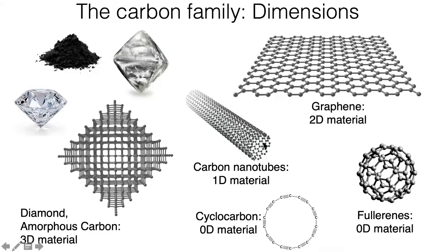Now let's go on to carbon nanotubes. If you imagine you take that graphene sheet and roll it up into something that looks like a toilet roll tube, you can see the hexagon all wrapped around in the tube. It can't grow out in any direction except from either end. So it's constrained to growing out in just one dimension. If you had a much wider sheet of graphene, would it curl around to make a larger circle? Yes, exactly. In principle, there is no size limit on how big you can make a carbon nanotube. They're called nanotubes because they are down at a very, very tiny scale. But if you had a big enough sheet of graphene, you could curl it back around on itself and bond it to form a very, very big tube.